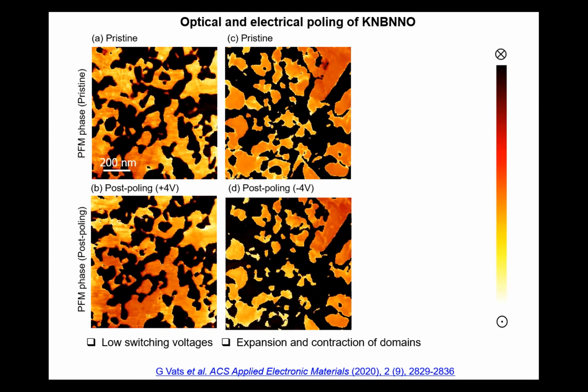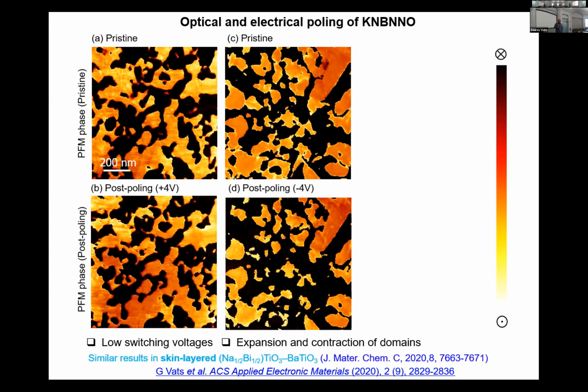And we have this expansion and contraction of domains rather than total flipping, as I showed in the case of PZT in the previous slide. So it's not switching fully, but the domains are moving. This kind of behavior I also observed in skin layered NBT-BT samples. So the idea is that the few top microns of the sample are showing this kind of skin layer. That's the terminology used, and they behave in this way.